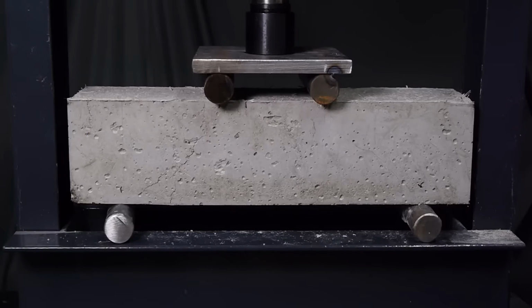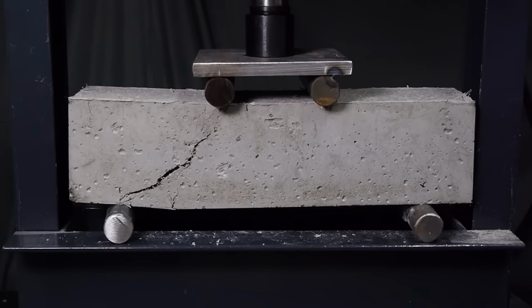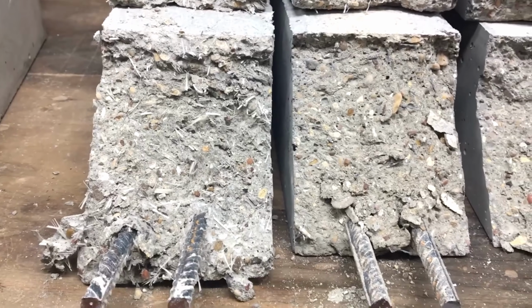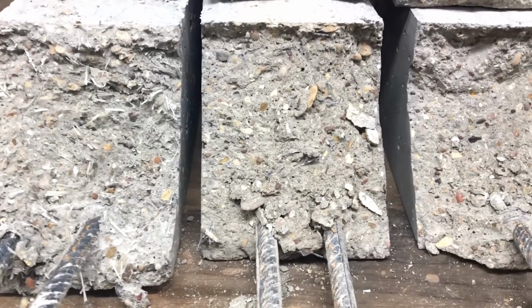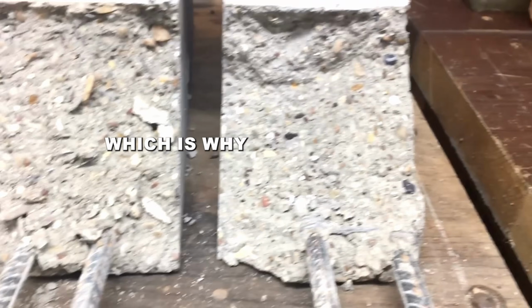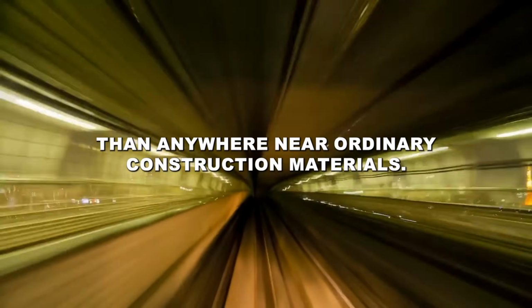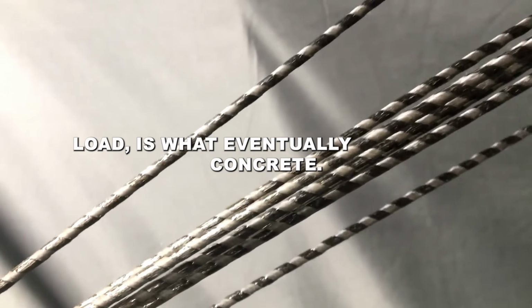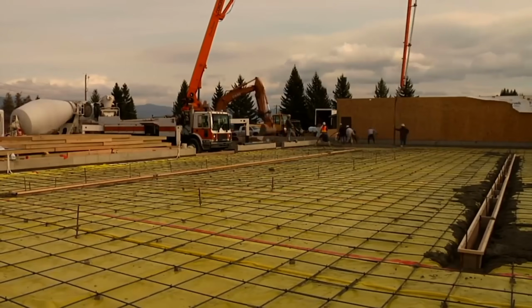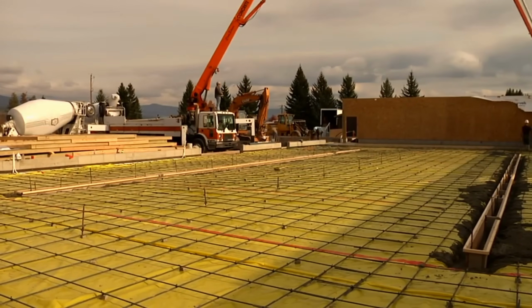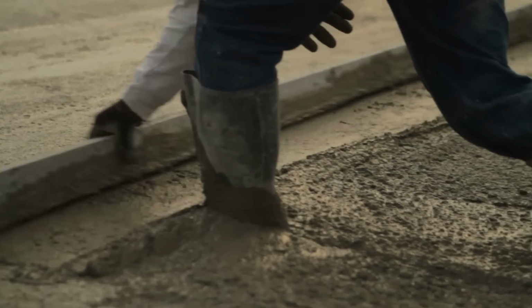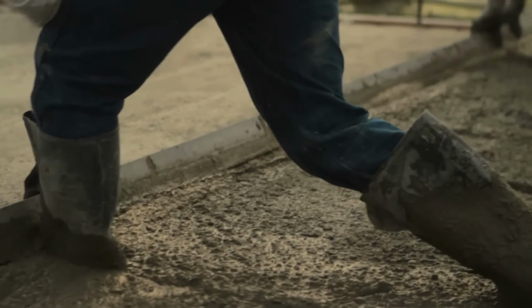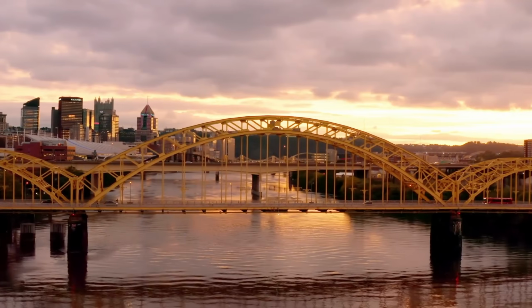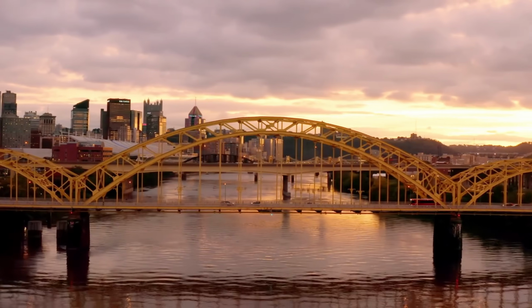Separate research on basalt fiber itself, rather than the finished bar, measured tensile strength as high as 4,800 megapascals in some samples, which is why manufacturers describe it as sitting between glass and carbon fiber, rather than anywhere near ordinary construction materials. For any structure where corrosion, not raw compressive load, is what eventually kills the concrete, that combination is close to ideal. The bond between the bar and the surrounding concrete matters just as much as the bar's own strength, and here basalt has quietly outperformed expectations too.